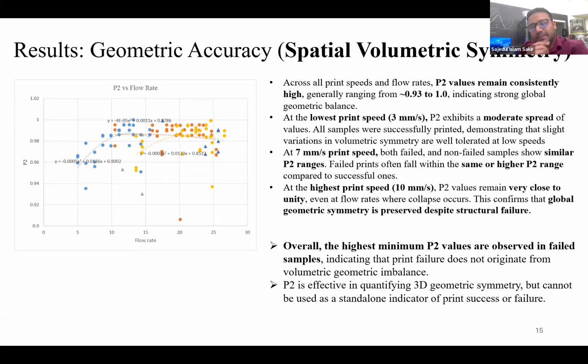So overall, we can say that the highest minimum P2 values are observed in failed samples, also indicating that the print failures do not originate from the volumetric geometric imbalance. And P2 is effective in quantifying 3D geometry symmetry, but cannot be used as a standalone indicator of print success or failure. So, P1 and P2.